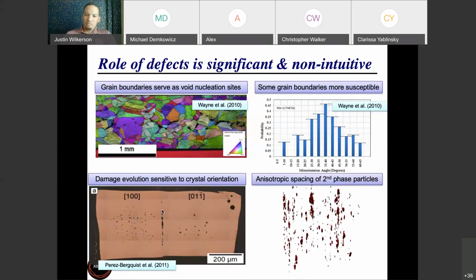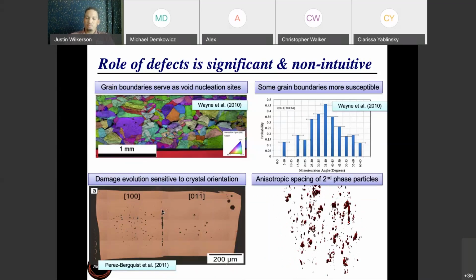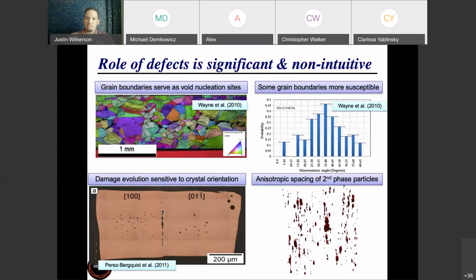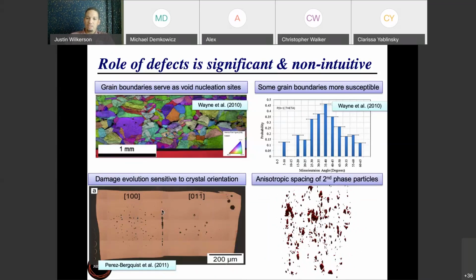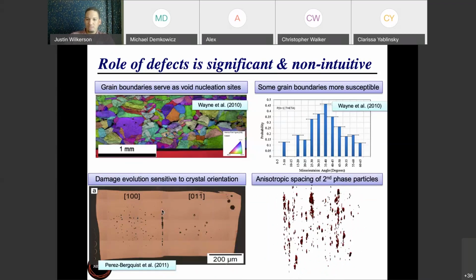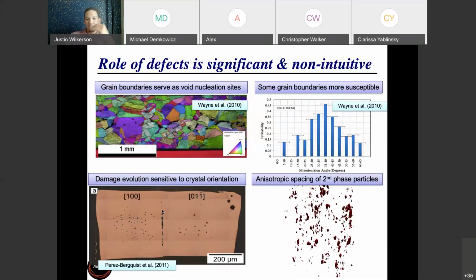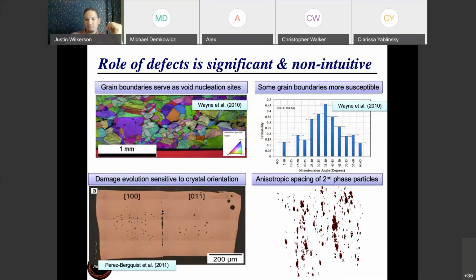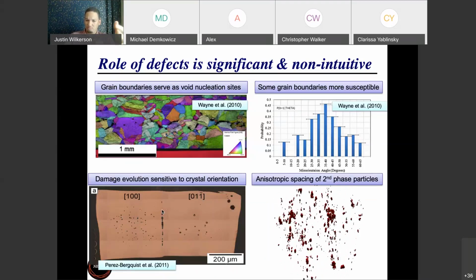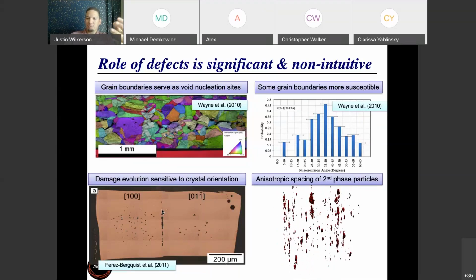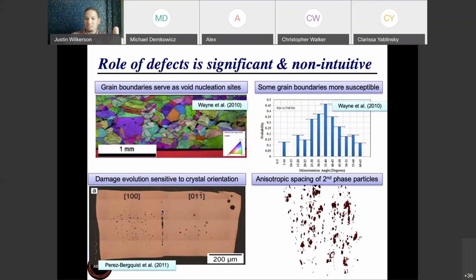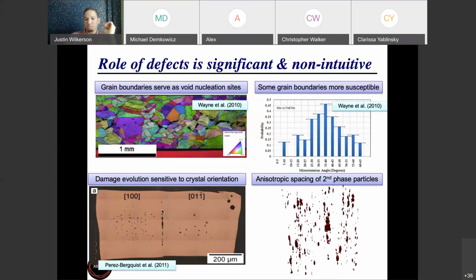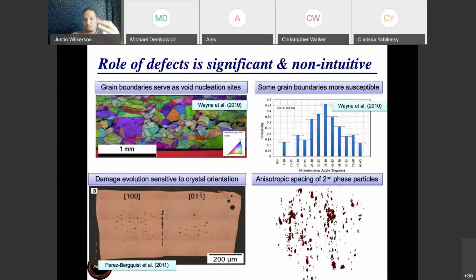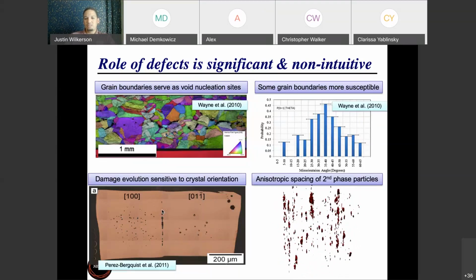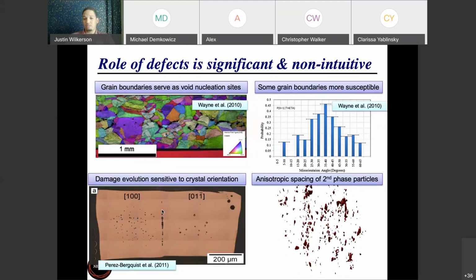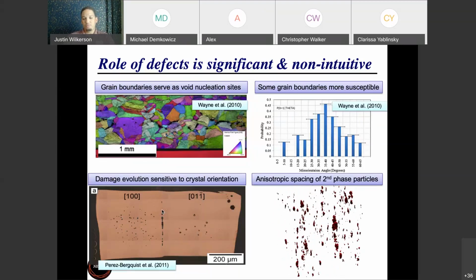Okay, and then voids tend to nucleate from grain boundaries, and if they don't, then they tend to nucleate from second phase particles. And those second phase particles can be quite complex. So this is a micro CT image of second phase particles in an aluminum alloy. And voids can nucleate from any one of these second phase particles. And so if you want to build a real physics-based model, then this would be the information that you'd have to import into that model. You'd have to know things about the spacing distribution, the size distribution, as well as the orientation distribution of these second phase particles.